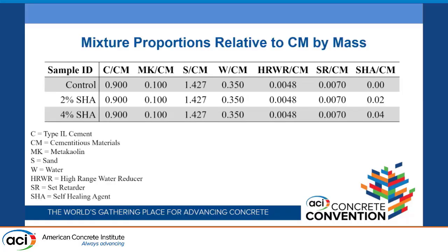Now, to test this hypothesis, we did a little bit of due diligence on the back end. We've done some testing with 3D printed concrete before, and we have our baseline control mixture, which includes a 10% addition of metakaolin, as well as a sand to cementitious material ratio of 1.427 and a water cement ratio of 0.35. We also include a high range water reducer and a set retarder just to extend our open window.